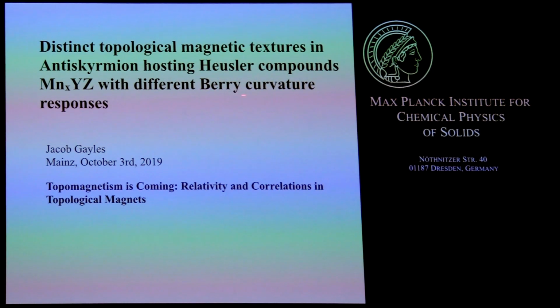The title of the talk is Distinct Topological Magnetic Textures and Antiskyrmion Hosting Compounds, MnxYZ, with different Berry curvature responses. The idea is that we look at certain compounds and really try to fight with this sandbox of materials to understand the underlying mechanisms that stabilize magnetic textures, and we want them to be topological. Then from that, you have some texture, you apply some field and you get some response. This is what we mean by Berry curvature response. Maybe Maz would like to say something like a hyperbolic response, but I am not so good with hyperboles.